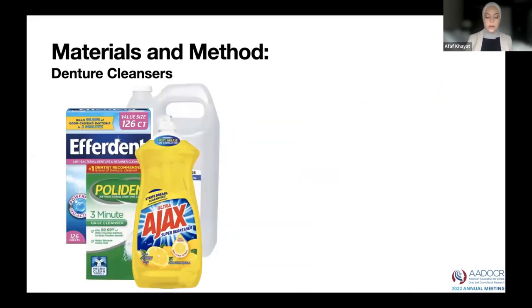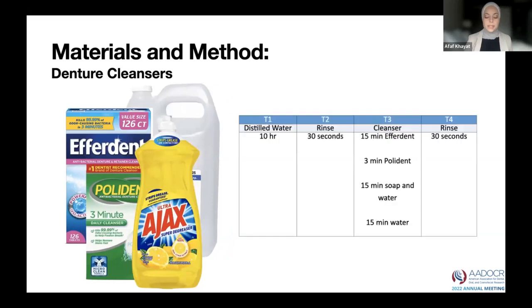Specimens were stored in distilled water at 37 degrees Celsius in between treatment cycles. They were also rinsed in between treatment and storage. The specimens were immersed in either Efferdent for 15 minutes, Polident for 3 minutes, soap and water solution for 15 minutes, or water for 15 minutes, as recommended by the manufacturer's instructions. This cycle was repeated 28 times.